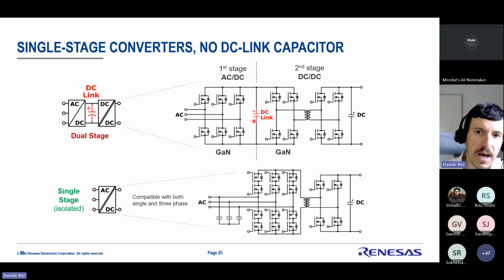But there are topologies in the literature that can actually do the same thing with a single stage. You can see here a rearranging of the architecture. Now at the primary side, the one facing the AC, we don't have the DC link anymore. But now we have transistors connected back to back, because we need to block the AC voltage both in the positive lobe and the negative lobe. So this is a topology that allows removing the DC link capacitor. However, if you do it with discrete devices, now you have more transistors. So there's more transistor count, and it becomes a little bit cumbersome.